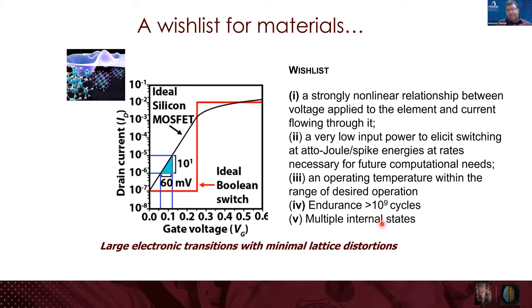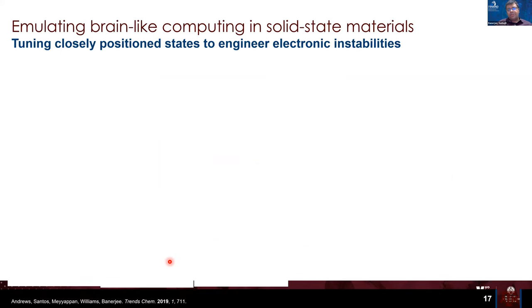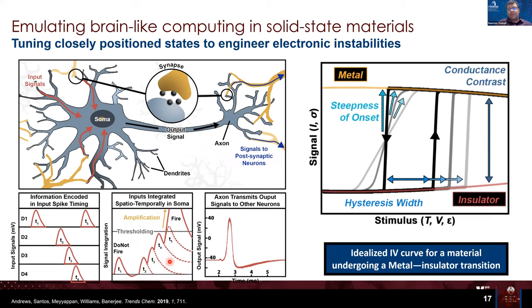So as a first descriptor, I think what has become often quite clear is that we would like to see large transitions in conductance, but without a lot of things moving around, without a lot of lattice distortions, because the more you have these, the more entropy dissipative these are. And so, if I were to get one wish, it would be: how do I get large electronic transitions with very minimal lattice distortions, right? And so this is our goal.